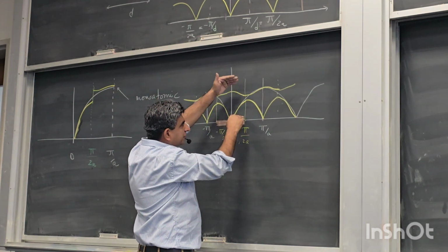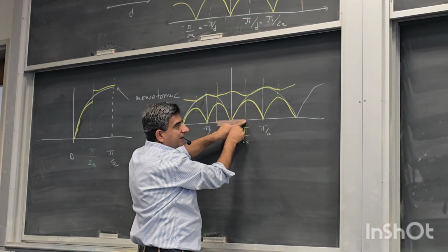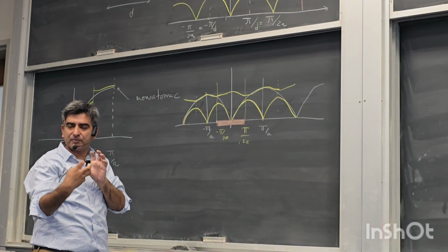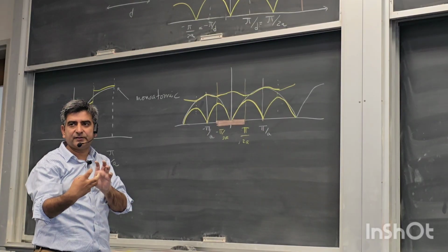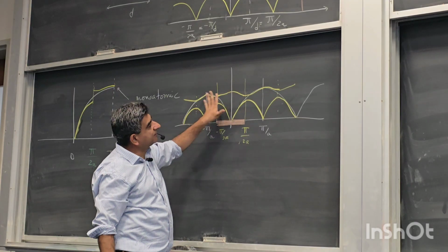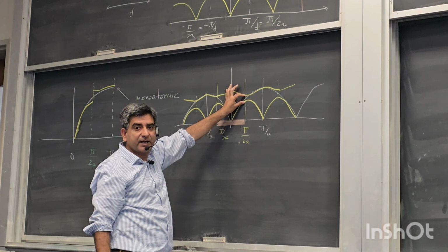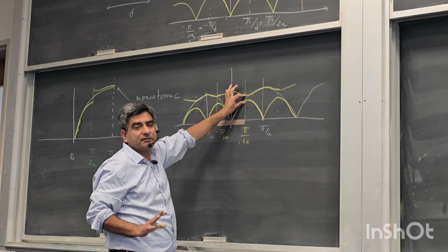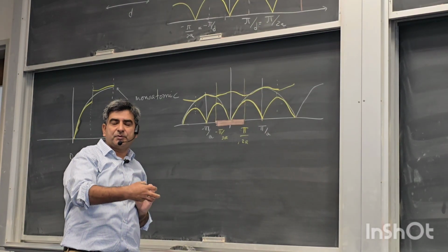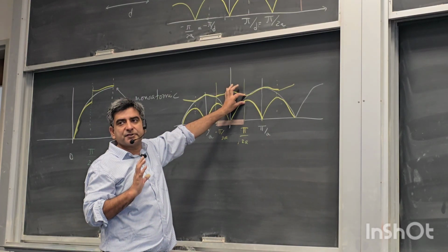So this white curve for the monatomic case has split asunder. It has shown a fissure at this zone boundary for the diatomic case. So this white curve has now been split when the two masses are different, or the two objects have different chemical identities. So a gap has appeared inside this dispersion relationship. It's a kind of band diagram, and this gap is a kind of band gap for mechanical waves. Whenever we introduce the additional kind of atom in the diatomic case, a gap has appeared in the dispersion relationship.